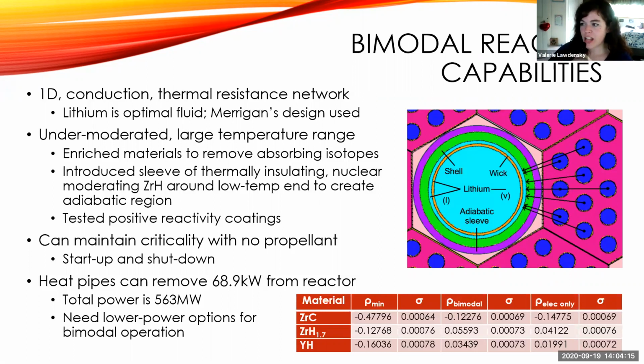And in this particular design, I chose a lithium heat pipe based on a very thorough experiment by Dr. Merrigan. He used a mostly molybdenum shell and wick, and we just talked about how great that material is, to move the heat and sustain the heat pipe. The green section in the diagram is the shell itself, and the blue, orange, and blue are parts of the heat pipe. You can see the lithium and the sections there.